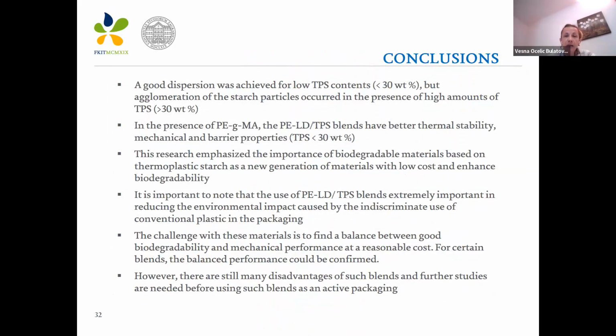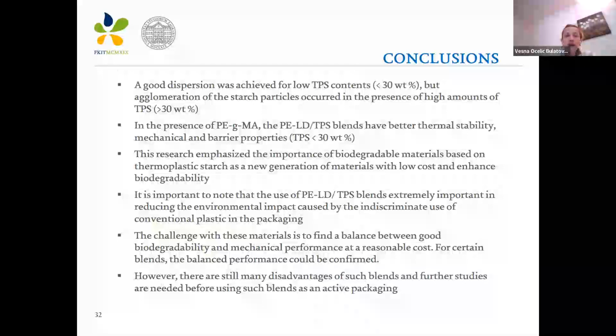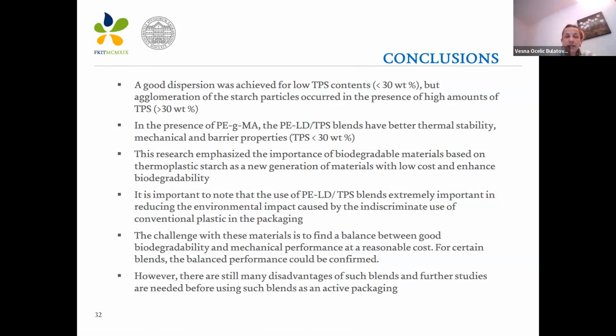And we come to some conclusions of our research. We say a good dispersion was achieved at low TPS content, but agglomeration of the starch particles occurs in the presence of a high amount of TPS. Blends with the compatibilizer have better thermal stability, mechanical and barrier properties. This research emphasizes the importance of biodegradable materials based on thermoplastic starch as a new generation of materials with low cost and enhanced biodegradability. It is important to know that the use of these blends is extremely important in reducing the environmental impact caused by the indiscriminate use of conventional plastic in packaging.